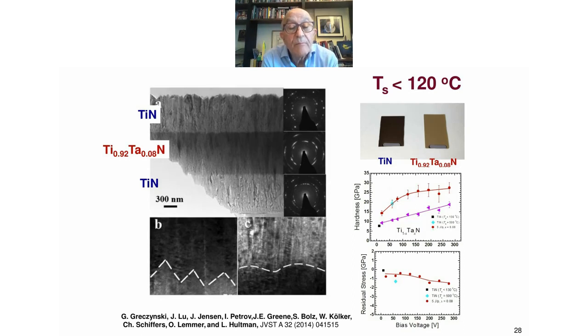When we stop the tantalum irradiation, the pores immediately appear again. Now, if you look at the hardness, the top curve, the red curve, is for the tantalum bombardment. And you can see that we can reach about 150 volts, where the curve plateaus at a relatively high 25 gigapascal. If we do the same thing with titanium, the bottom curve, we can never reach that hardness and density.